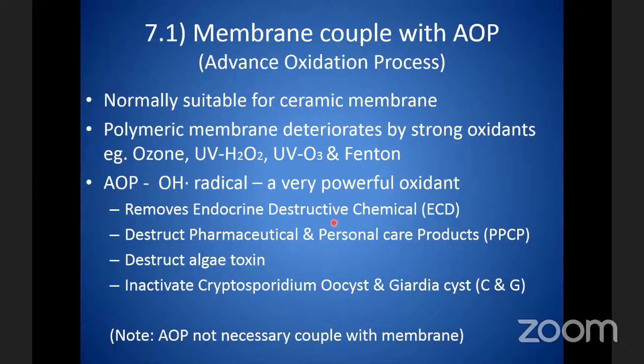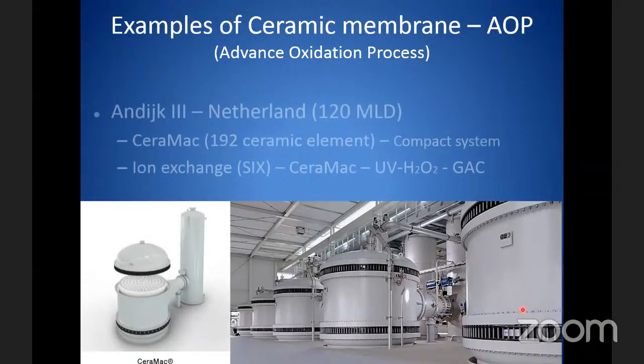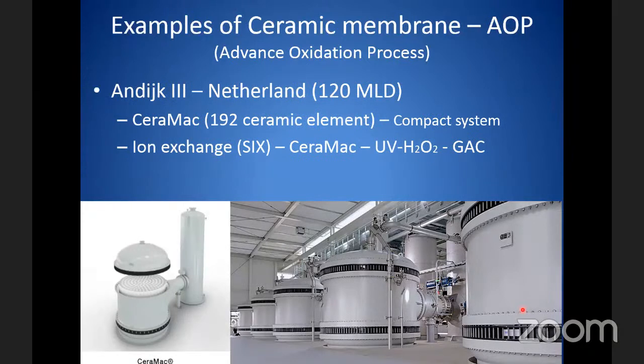All those pharmaceuticals are mostly organic. It will oxidize them and break them into smaller pieces so that they lose their original effect. It also destroys algae toxin. It will inactivate Cryptosporidium and Giardia cysts in this system. But note that AOP does not necessarily have to be coupled with a membrane. You can have other systems. Anyway, the membrane will remove the C and G itself already. But if you put the AOP after it, before it, or in any of the system, it will inactivate the C and G. So these are another example that they installed, this one is in the Netherlands.